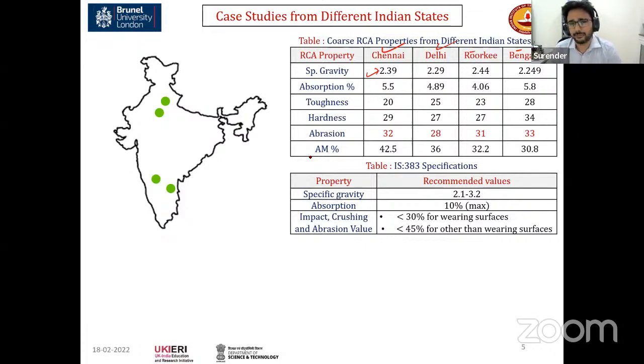Okay, these are the other physical properties that are required. So in India right now we have the codal provisions. In 2016 we had codal provisions to use recycled concrete aggregates, right? Like Rohit has already mentioned, 25%, 20%, or 100% for lean concrete. So whatever aggregates we have collected from different plants seem to be satisfying the norms, at least for the non-wearing courses, like the pavement base layers, not for the wearing courses, right? It's not only the specific gravity and water absorption, but we also need to characterize the other physical parameters.